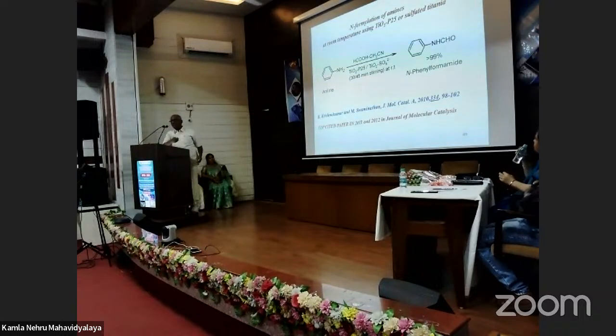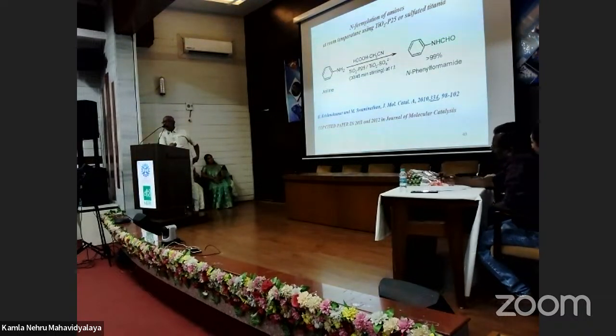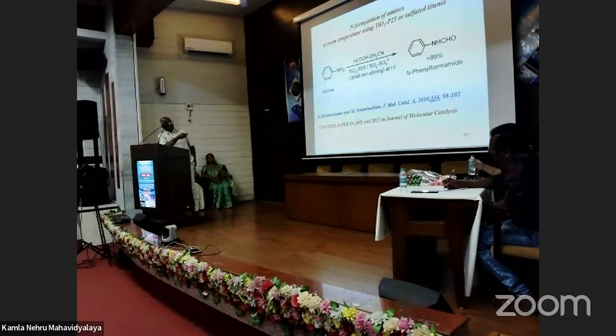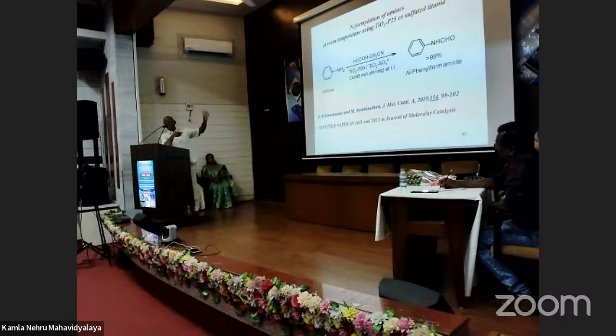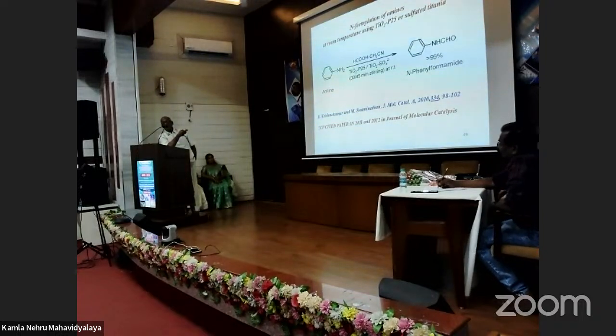And this N-formylation reaction, N-formyl compounds are industrially very important, because they are used in industry for so many applications. So these N-formylation reactions, whether on a primary amine or secondary amine, can be carried out using formic acid and acetonitrile. You can use either TiO2 P25 or sulfated TiO2, but sulfated TiO2 is found to be more efficient and also recyclable, whereas TiO2 P25 is not recyclable. You can see that just 30 to 40 minutes of stirring at room temperature can give 99% conversion of N-phenyl formamide.